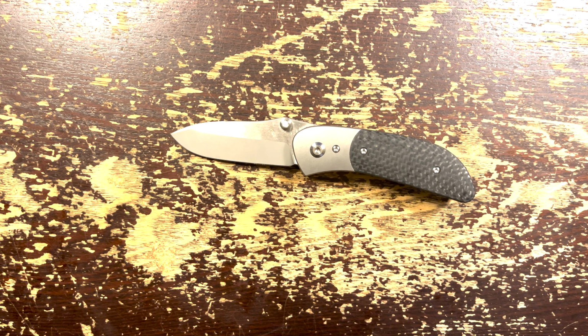But I noticed that dendritic cobalt cuts differently, not just longer. After some experience, I found that I was able to feel that toothy edge, like I was using a tiny pocket saw. With that working edge, I could cut things using a normal technique just fine and could get about the results that I would with a steel blade that is medium sharp. But if I cut using a slight sawing motion, suddenly the knife would slide right through anything, as though it were much sharper. This was fascinating to me, and it was very noticeable with cardboard.